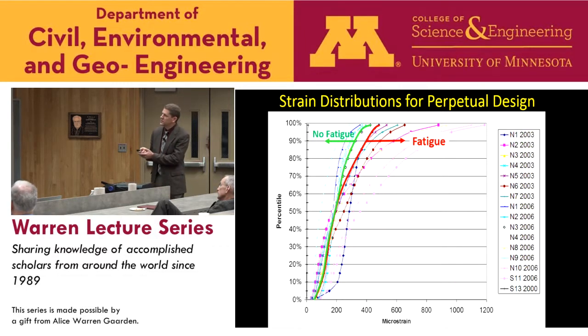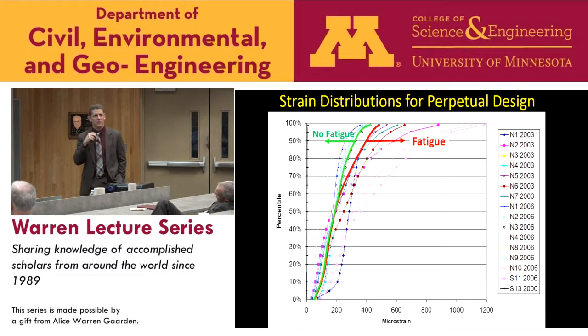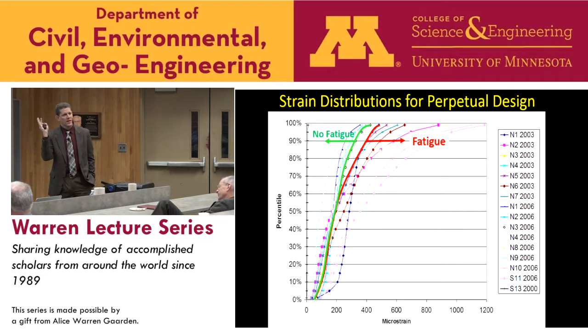And what's really interesting is that down here everything is kind of mixed and crossed over and so on. But at about the 60th percentile or so, we have a nice divergence between those two curves. And what we're able to do then is really look at this curve as sort of an upper bound for structural pavement design. We can use that as kind of a control distribution when we're designing using Monte Carlo type approaches where we generate strain distributions. We can design, see what we get, and then compare it against a distribution like this, and then make a decision. We need to make it thicker, thinner, or what have you.